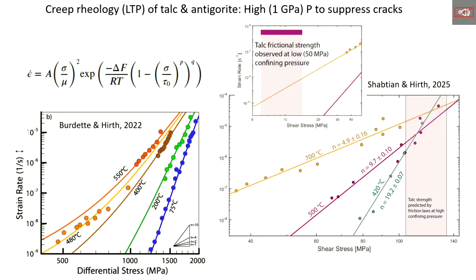And with that type of technique, you can acquire a lot of data at very, very low strain rates in the range of 10 to the minus 8, because you get the steady state in a really small amount of strain. That's a really important part of that. And so he did this in antigorite and found this really beautiful data set that shows the hallmark of low temperature plasticity in serpentine. Hannah came into the lab just at that time and her experiments were designed to study pressure solution. But what did we find? We found low temperature plasticity in talc.